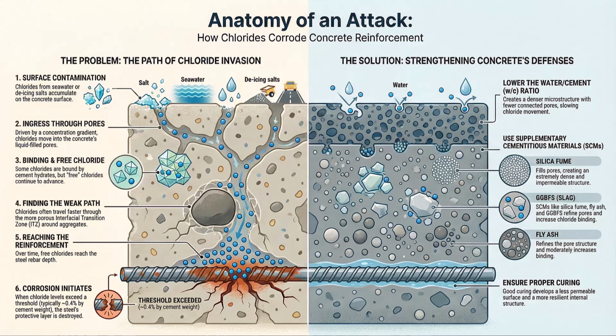You're not just fighting the heat. You are fighting the very chemistry of accelerated material decay. And the core conflict here, the real enemy, is something called chloride diffusion, basically salt getting into the concrete. And it causes this rapid, devastating corrosion in the steel reinforcement. Our sources paint a really clear picture. This environment creates a perfect storm of factors.